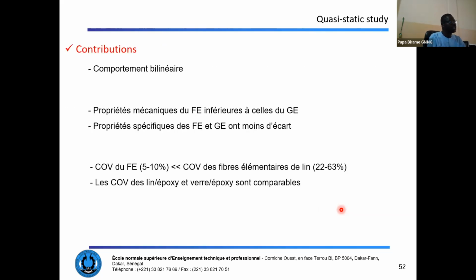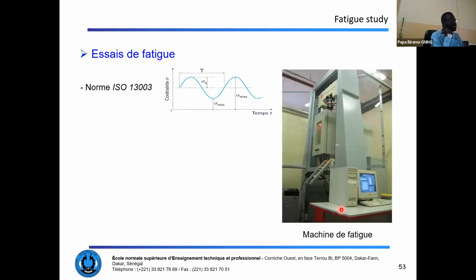So we can note that the Flax epoxy composites have bilinear behavior. Their mechanical properties are lower than that of glass epoxy composites, but due to the lightness of the Flax epoxy, the difference becomes small when these mechanical properties are divided by the density. And we can see that the reliability, that means the overall variability of Flax epoxy composites, is at the same level of the glass epoxy composites. Sorry for the French in this slide.